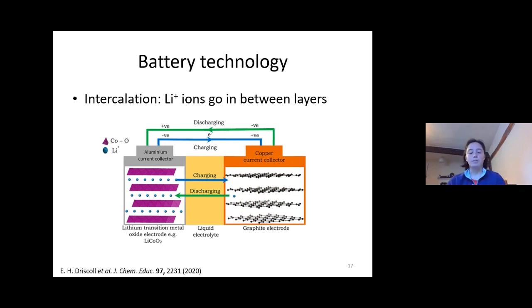And this is called intercalation, which is where you're putting something in between the layers. And what we'd see experimentally is that we measure the distance between those layers, and that will increase as lithium ions go in between. And then as we take them out again, or as we take them out of the other side, the layers get closer together. That's de-intercalation, removing the ions from the layers, and the layers go together again. And the battery works because this cycle can happen many, many hundreds of times.